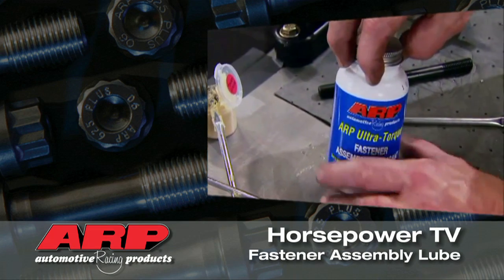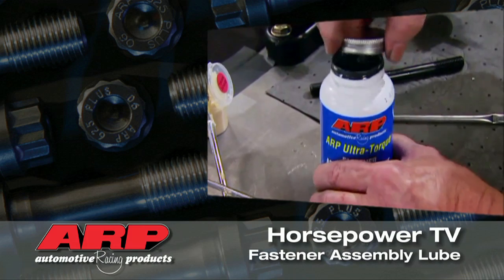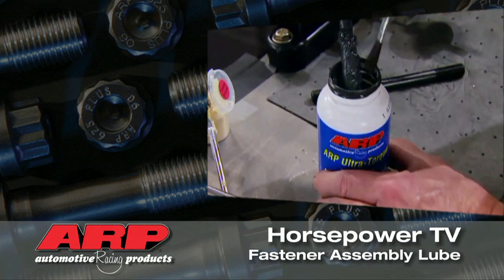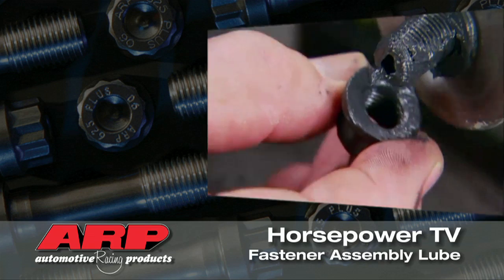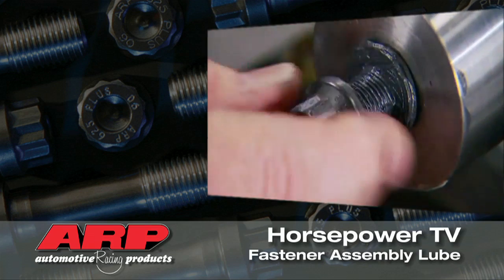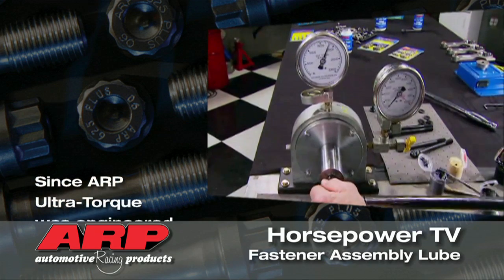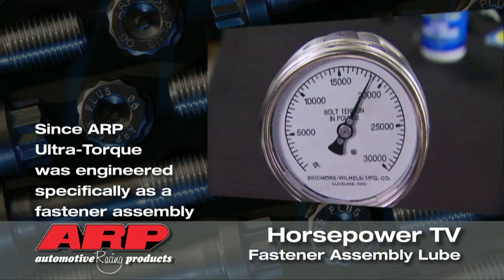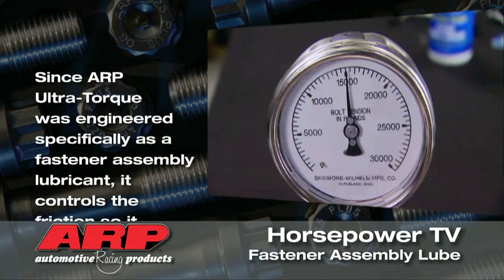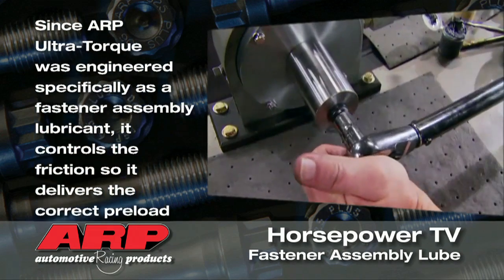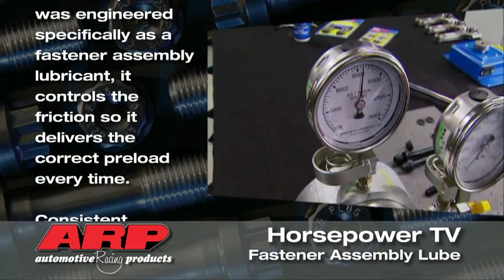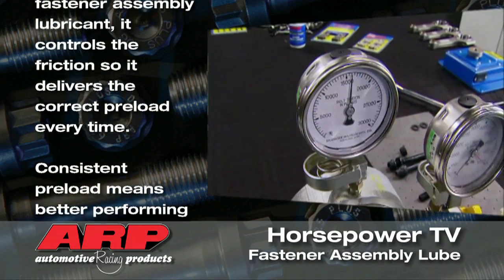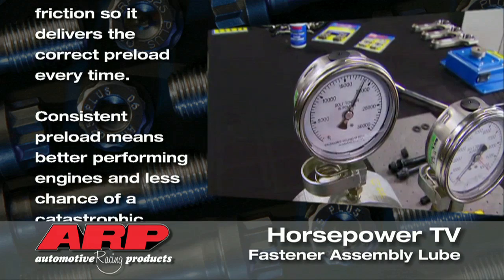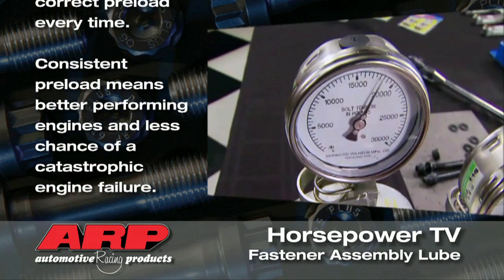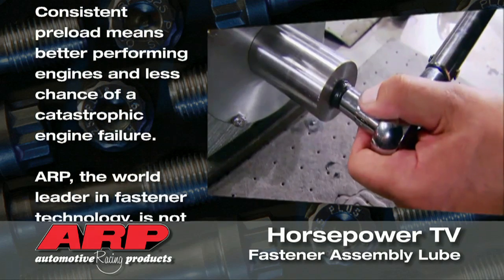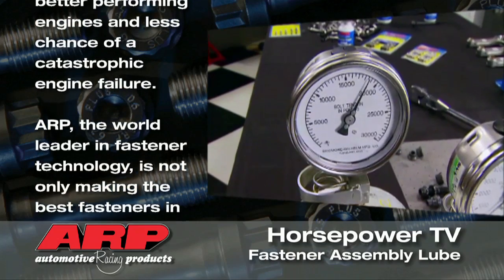Finally, ARP's Ultra Torque Lube, made without moly or metals, and formulated to achieve the target preload on the first torque cycle with repeatability. Plus, it prevents seizing and galling on threads. On the first torque sequence, we're at 18.5, which is right in the ballpark. But ARP claims Ultra Lube will maintain that preload level within 5% on all following torque cycles. And it does on the second and the third, and for 2 more cycles before we call it quits.